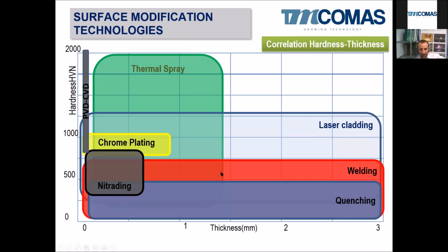So at the end, as a summary of all these surface modification technologies, I have made a very simple table which correlates hardness and thickness. And you will realize quickly that if we want about 500 Vickers and a 0.5 millimeter thickness layer, there are plenty of technologies that will be suitable for that layer.